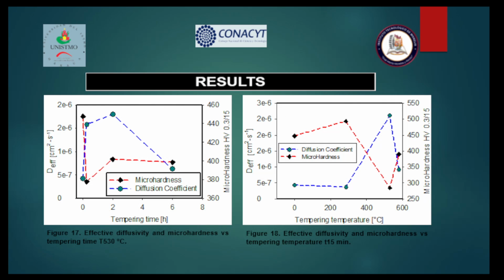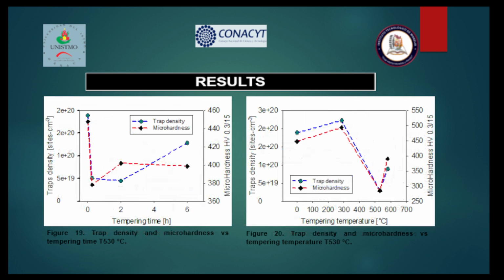With respect to the microhardness and the diffusivity of hydrogen, an almost inverse behavior is observed. This means that there is the presence of traps that prevent the diffusion of hydrogen, which in turn generates hardening of the material. This phenomenon can be verified with the graph that relates the microhardness with the density of traps, which have an almost identical behavior, evidencing the presence of hydrogen traps as well as a secondary hardening phenomenon caused by the alloy carbide that precipitates in the four tempering states.